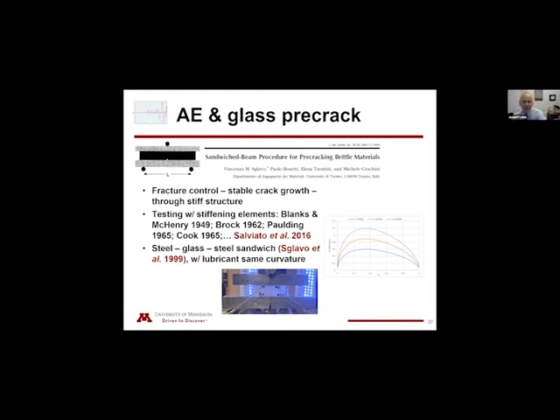So we went to using a sandwich beam. This was recommended to us by our colleagues in Italy. And this is a very nice paper that was written by a group in Trento. Certainly testing trying to get stable fracture using stiff elements is not new. Very nice work was done at Northwestern. But this is a very simple approach, and it was successful for us.